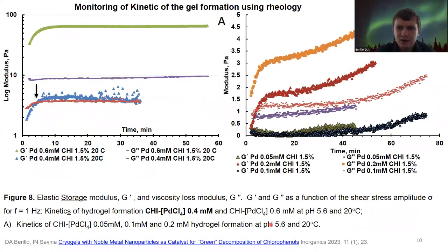And this correlates well with rheology data, and as one can see, we have a crossover between G prime and G double prime at approximately 3-4 minutes, which corresponds to transformation of the sol to gel state, and that was observed for concentration 0.4 millimole of palladium in CHI solution.